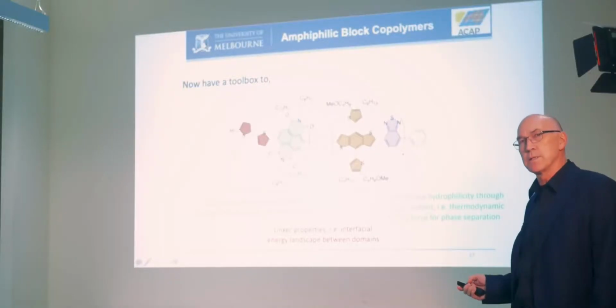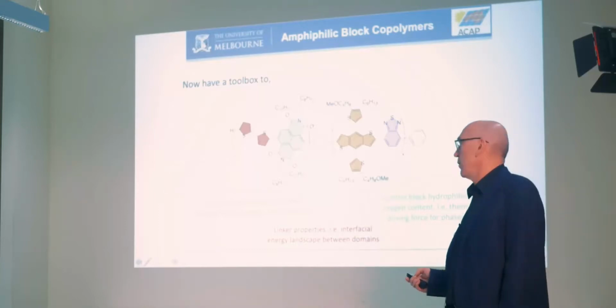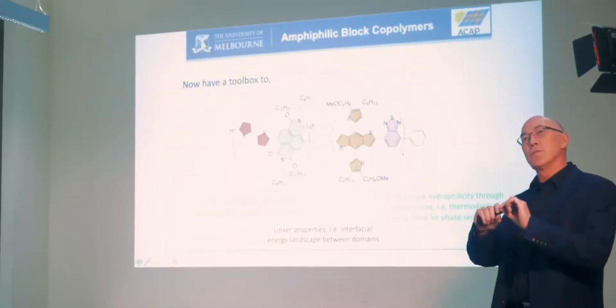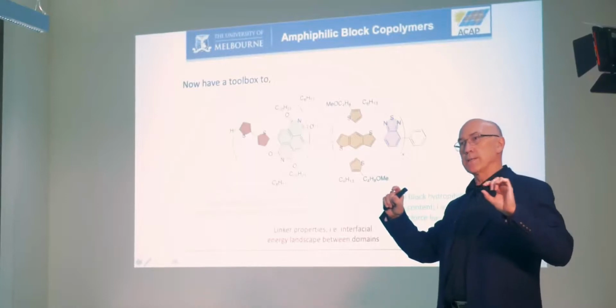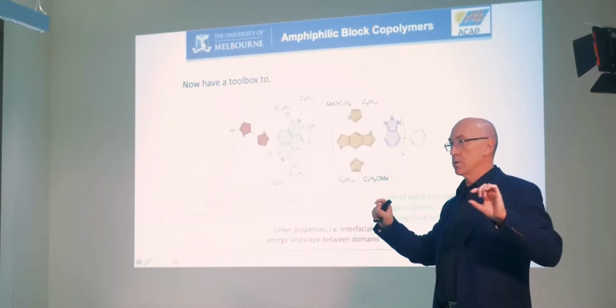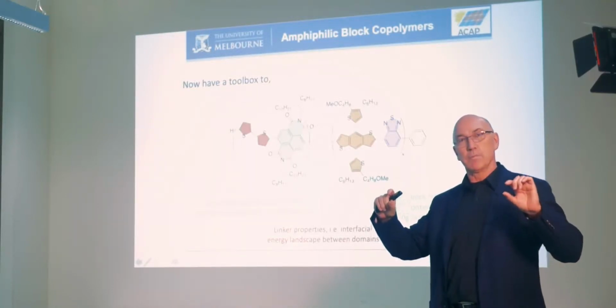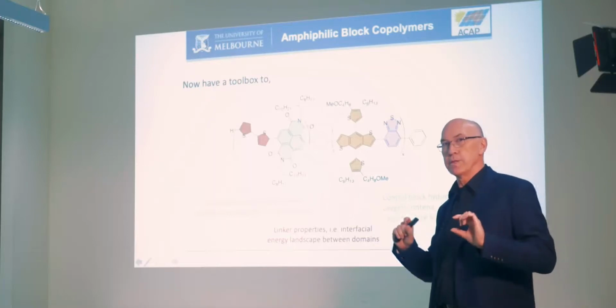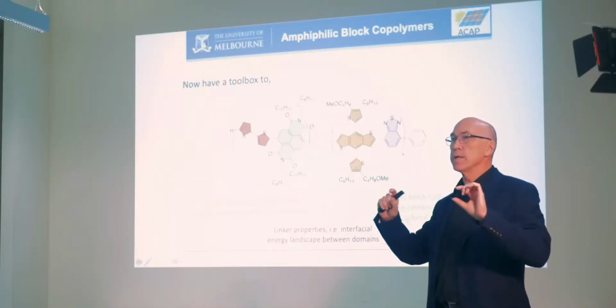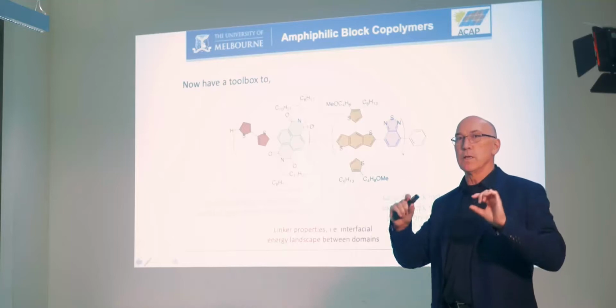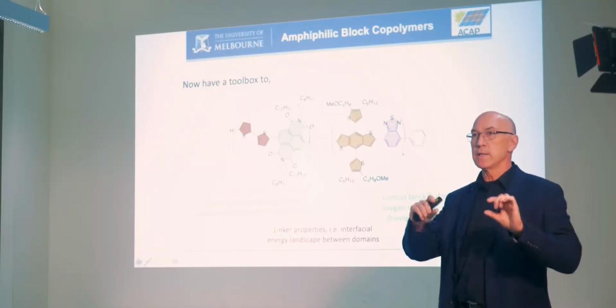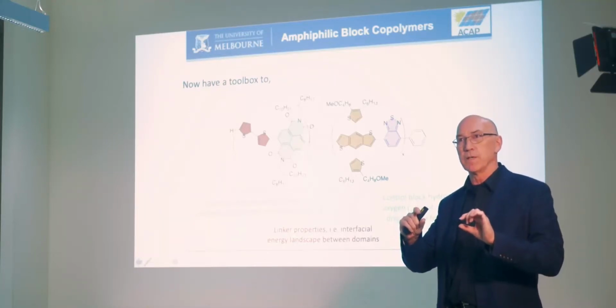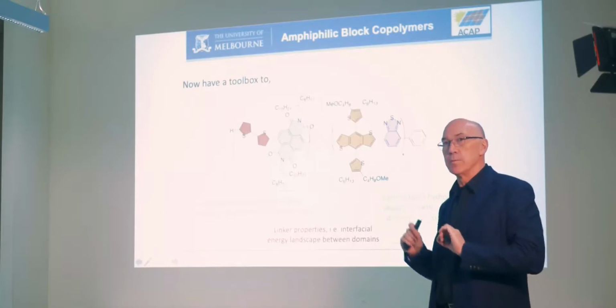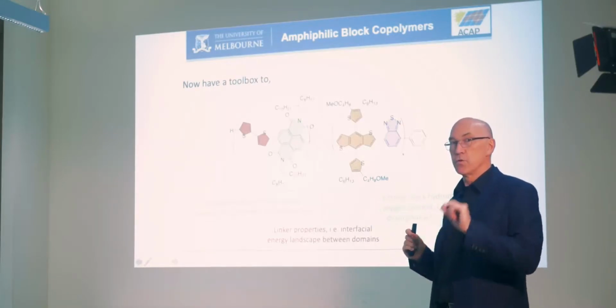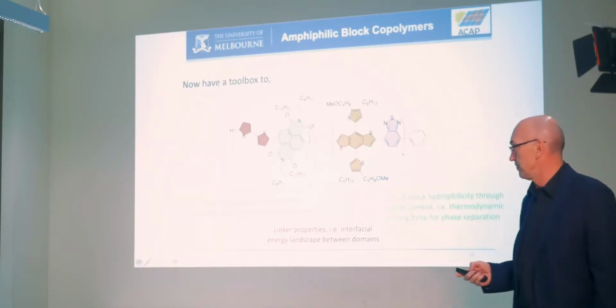And the little bit here in the middle, it's only small in this one, but this is the linker. And so we can substitute this linker to effectively control the energy landscape between the two blocks. And so we're now set up. If we hadn't had COVID, we would have finished some of that work now, but we're now set up to be able to really look at domain size and energy landscape at the interface on the performance of these solar cells. So that's work still to be done.